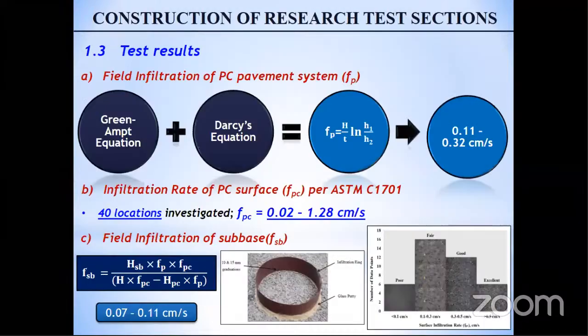Now moving forward, the first objective of the study was to construct the test sections, obviously, which was accomplished with huge success. Then the second aspect was to investigate the field infiltration of the pervious concrete pavement system, which included both the surface as well as the sub-base layer. So you see the Green-Ampt equation as well as Darcy's equations were combined together, and it was found that the infiltration rate of the entire system varied somewhere between 0.11 and 0.32 centimeters per second.